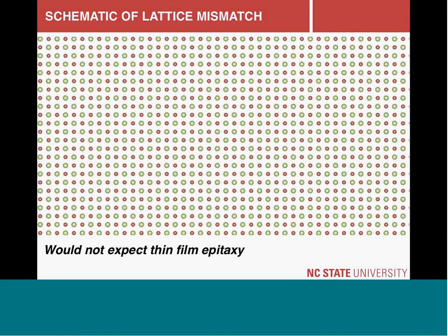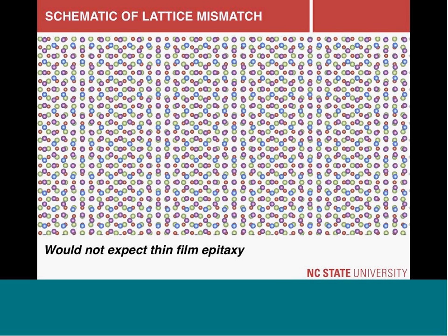Here's the gallium arsenide substrate surface. Okay. Putting the telluride on top of that, there's some alignment every now and again in terms of the periodic nature of this, but that's about 3 nanometers periodicity. There's not a match. So again, we would not expect this.